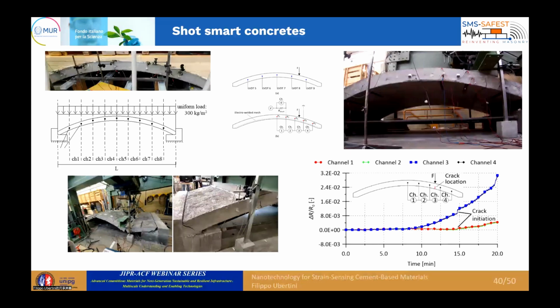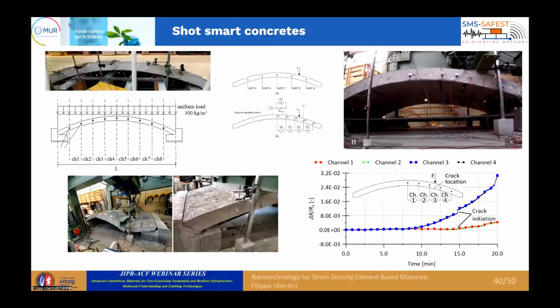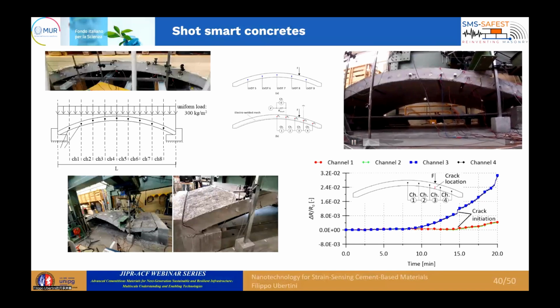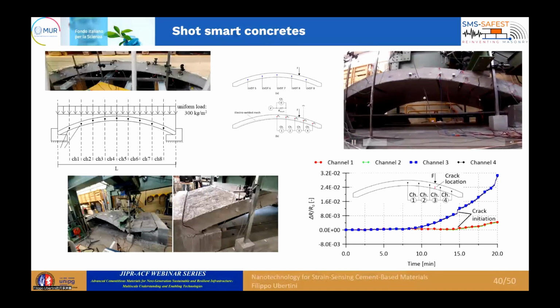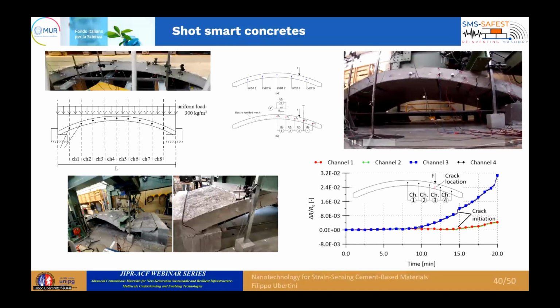Here is the experiment where we apply the force here, we measure displacement with LVDT sensors in these points, and we measure voltage drops across these pairs of electrodes here. Electrodes have the same length as the width of the vault. Here you see a video of the vault being tested to failure. This was a displacement control test. So this is a time-lapse video, but the test lasted several hours.